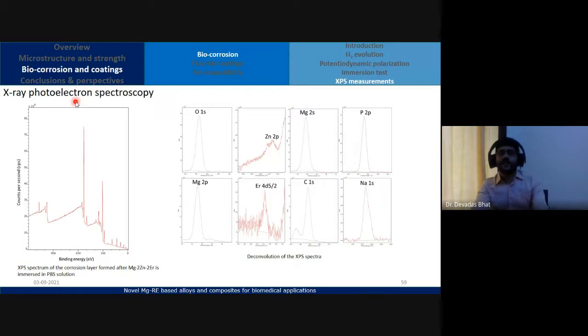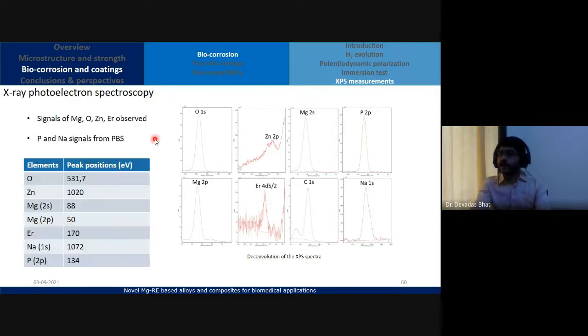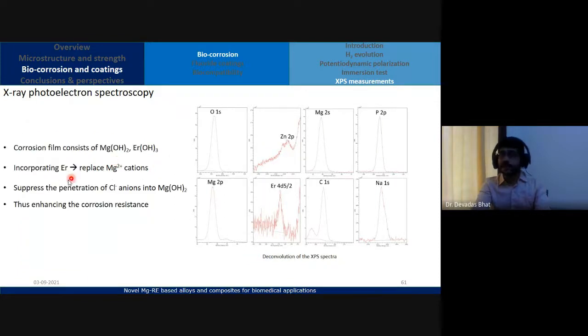All right, then there is another technique here called XPS, that is to study the surface layer. Because of these studies, we could see that the erbium element that we have used is found on the surface of the corroded sample. We could see that the Mg2+ cations were replaced by erbium, a higher atomic number element. The larger erbium atom replaces the smaller magnesium cation, and that will suppress the penetration of further chloride anions coming into contact with the film. So this is a mechanism behind enhancing the corrosion resistance because of the presence of the rare earth.